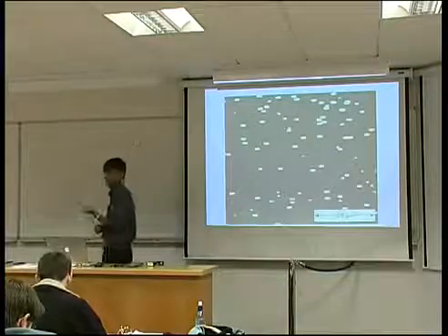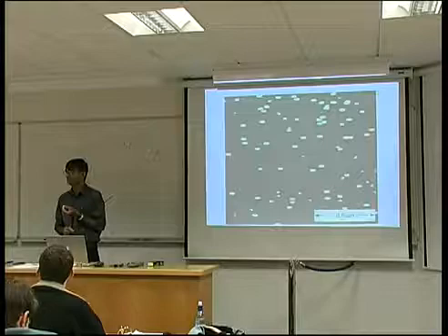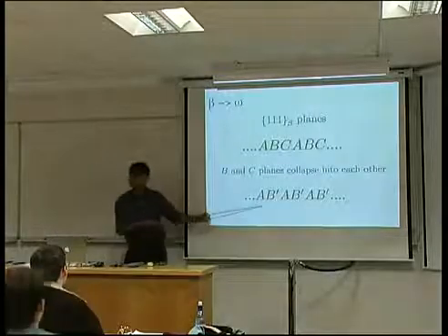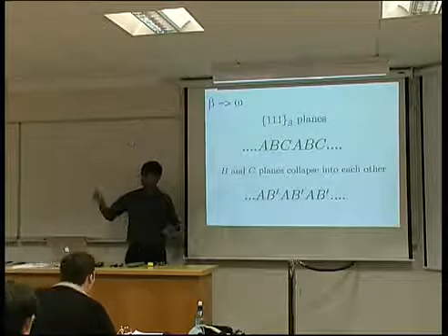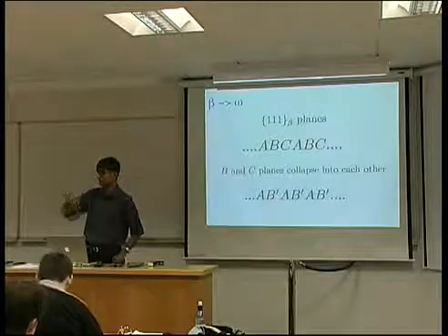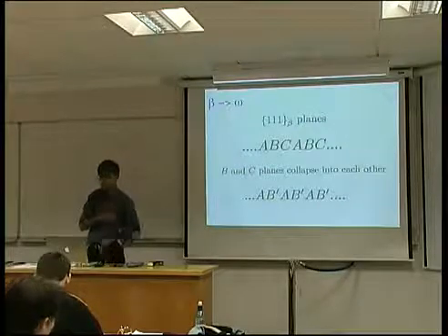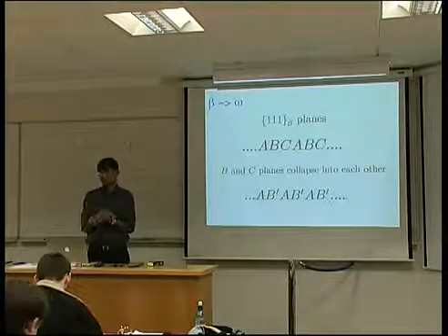this phase severely embrittles the titanium. So this is called the beta to omega transition. It has the most peculiar c/a ratio, which is far less than 1. Okay, far less than 1. So if you like, AB dashed is like a hexagonal, with a c/a ratio which I'm recalling from memory is about 0.6, it's in your notes. So it severely embrittles the titanium. And of course, it's a diffusionless transformation.